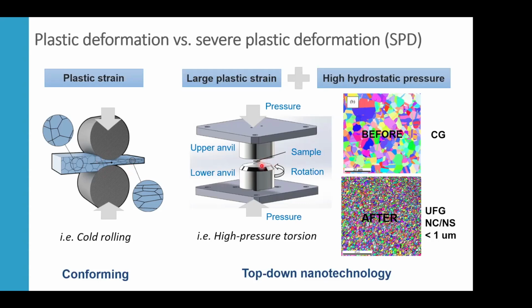Traditionally, we put a disc sample between 2 anvils, and these anvils are the ones that I mentioned before. It can be tool steel or a harder material if we want to process ceramics or oxides or some other hard materials, intermetallics, or high entropy alloys. And then we can apply high pressure and deformation by rotation of the lower anvil. So the rotation of the lower anvil will produce significant creation of dislocations and deformation, but the hydrostatic pressure will usually keep crack propagation at rest. So the material can accumulate a lot more crystalline defects, and these crystalline defects will evolve into usually bulk ultrafine-grained or nanocrystalline microstructures, as you see on the right.